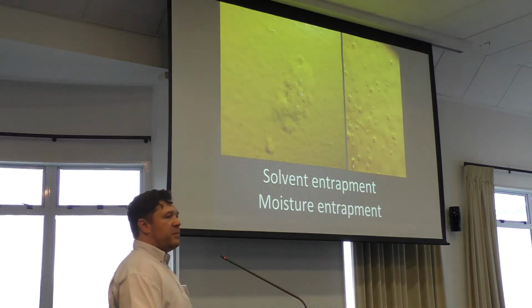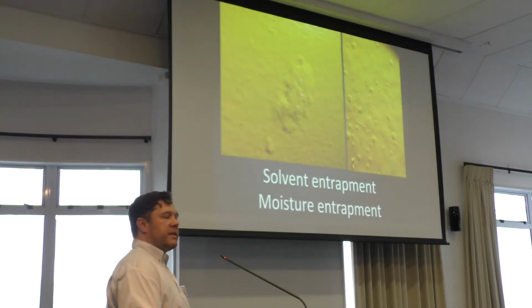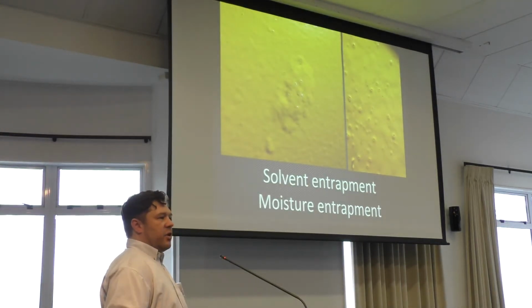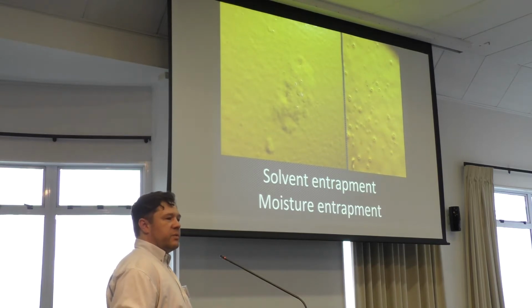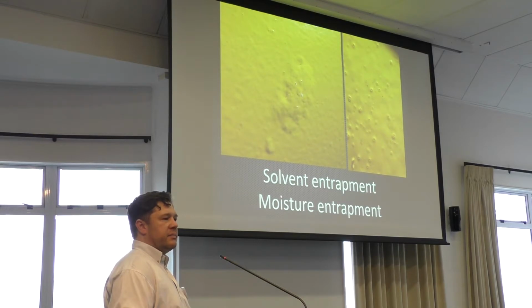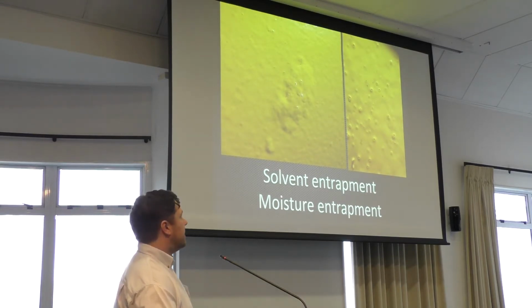There could also be bubbles in the coating. So if you haven't thinned your sealer, the air trying to escape is coming through a thick viscous paint, which then traps it as a bubble rather than just popping. If it's nice and thin, the bubbles will readily pop and they won't stay bubbles.